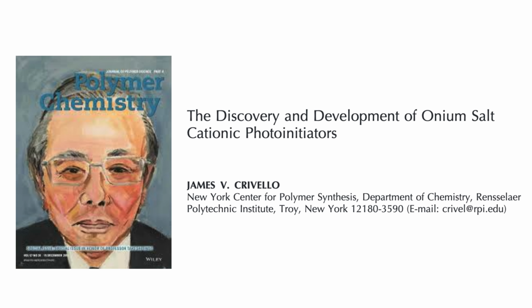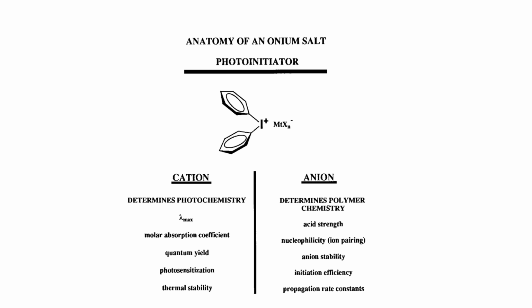Free radical UV coatings were under development at this time, but when it was concluded that a curing unit with 20 mercury arc lamps and a nitrogen purging system would be required, it was deemed too expensive, and alternatives were needed. This led to the development of onium salt photoinitiators for cationic polymerization and the first successful application with photo-curable epoxy generator core plate enamel. As the oxonium ion and carbocation are inactive to oxygen, there was no need for any nitrogen purging step.